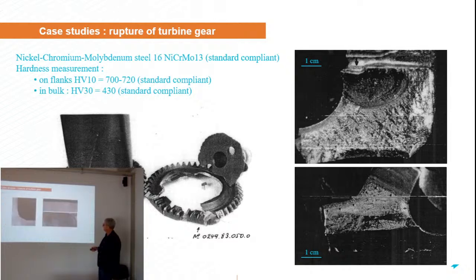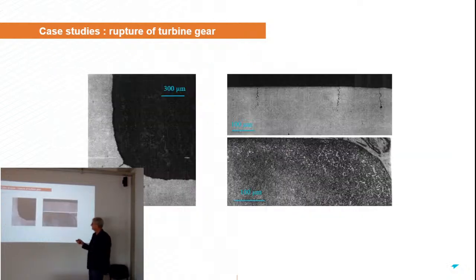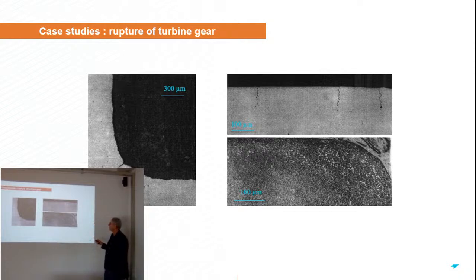fatigue fracture here. And when you analyze more closely, at a higher magnification, you can see that you get a lot of cracks, and that these cracks are precisely the size of the zone at the surface of the material, which was hardened using diffusion of carbon.